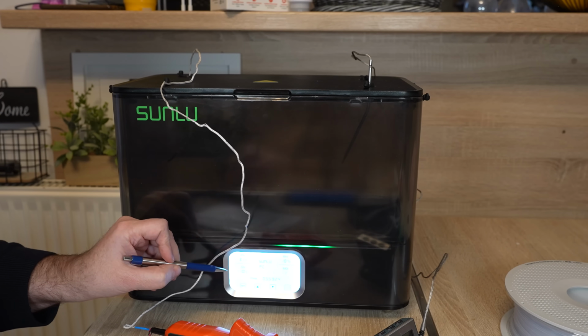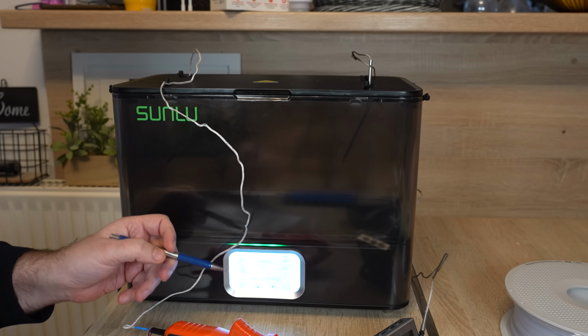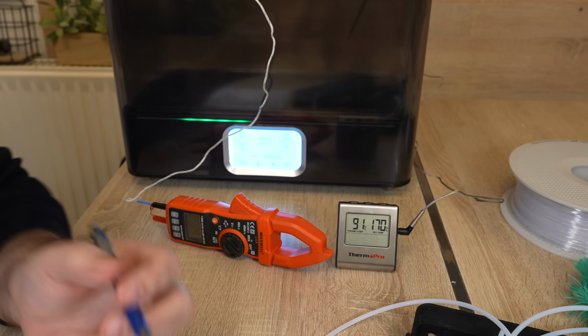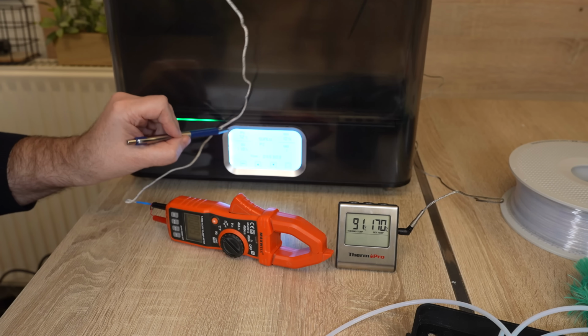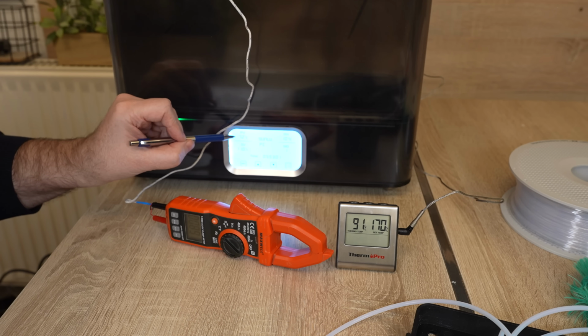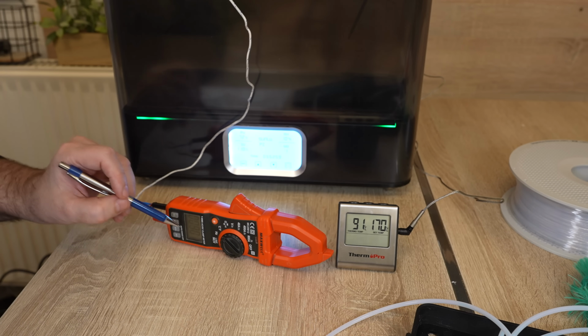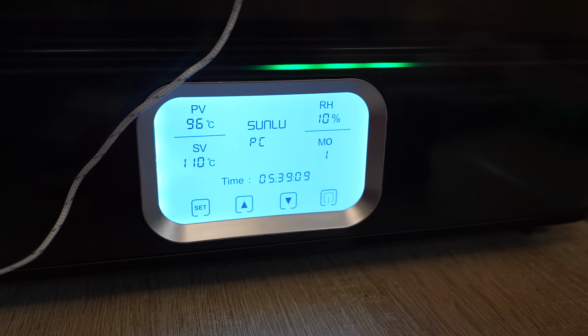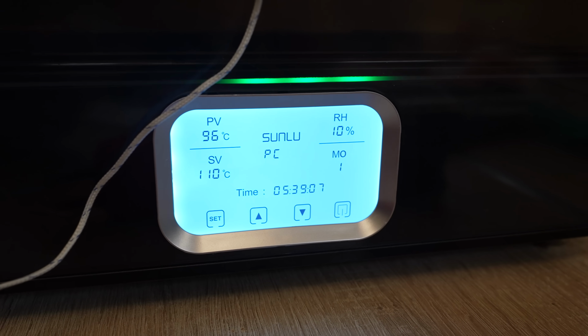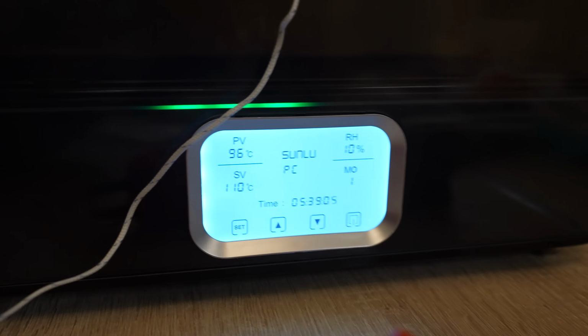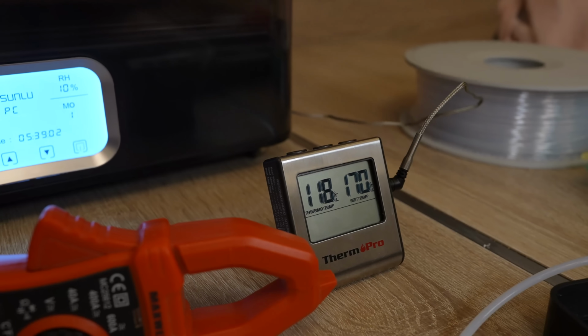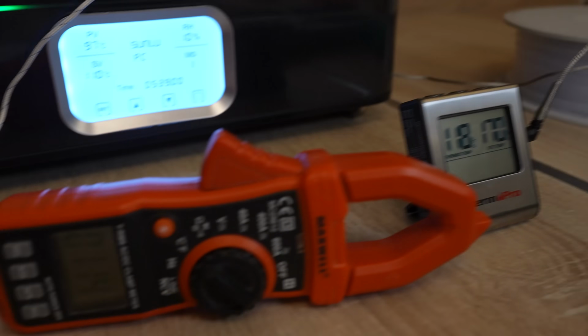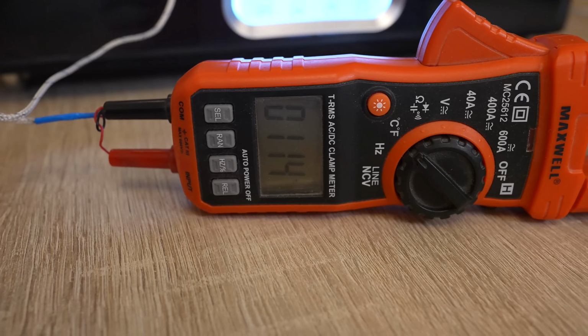The temperature is set to 110 degrees Celsius and the start temperature was 24. Only after 8 minutes it's already 72 degrees Celsius according to its own sensor, 91 and 89. After 20 minutes, according to the oven sensor, 96 degrees Celsius inside. On the hot side it is 118 and on the other side 114 degrees Celsius.